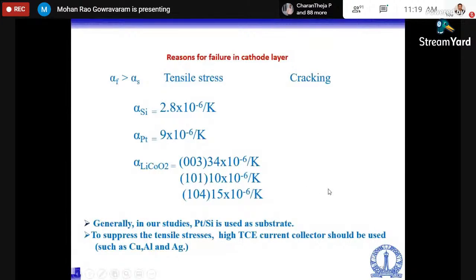The expansion coefficient alpha of silicon, that is your substrate, is about 2.8 into 10 to the power of minus 6 per Kelvin. Whereas that of platinum is 9 into 10 raised minus 6. Whereas that of lithium cobalt oxide is 34 into 10 to the power minus 6. So where is 2.8, where is 34? Nowhere it's matching. So what happens when you are annealing your film to get the crystallinity, because of the mismatch in this thermal expansion coefficient, it is delaminating. So this is not the ideal solution.